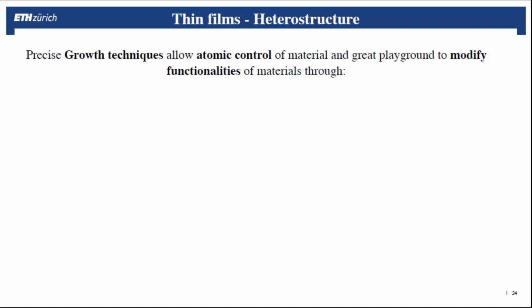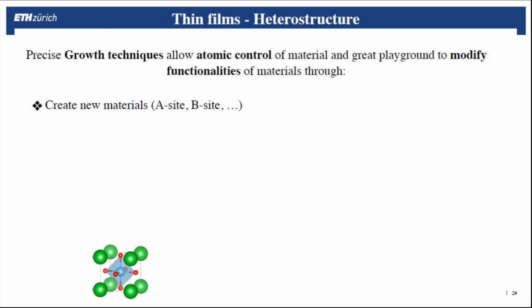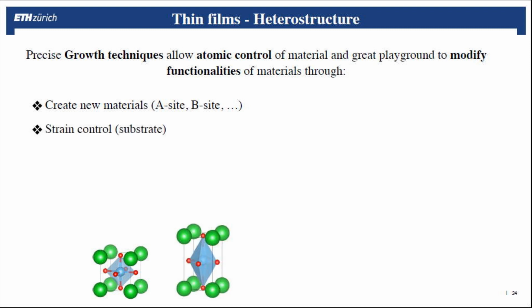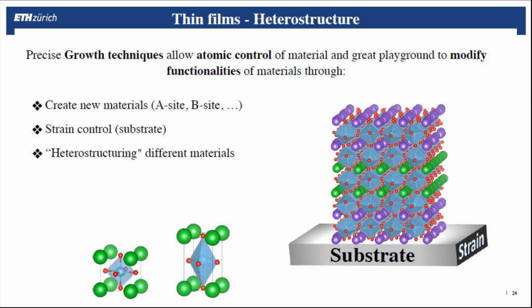In general, due to the growth techniques, one can create materials by choosing which atoms go in the A site or in the B site. You can apply strain in your material, as we saw, and that would result in enhancing polarization, for example. But there is more. Imagine that you have a substrate, which implies strain, and you grow on top one type of material, and then you alternate with another type of material.